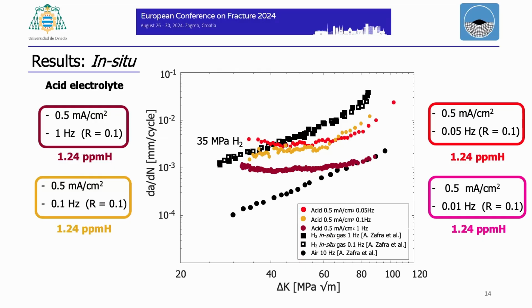We reduce it more to 0.05. And the same, at the beginning, the result is similar to the gas test, but the growth rate is constant. And when we decrease it to 0.01 hertz, the result was the same as for the gas test. So when we want to evaluate steel under electrochemical condition, it looks like you have to reduce the frequency significantly to obtain the same values as for the gas test.